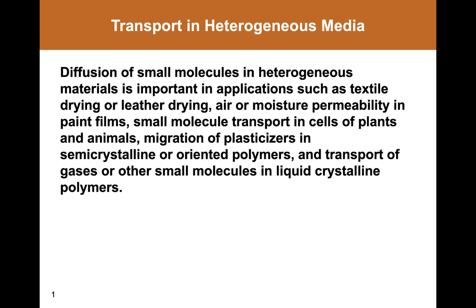And so this can be, for example, crystalline regions in a semicrystalline polymer are impermeable, but the amorphous region surrounding these crystalline regions typically is not impermeable. And so penetrant molecules that are diffusing under a concentration gradient through such an environment will have to go around those crystalline regions, and so the transport equations are modified as a result of the structural heterogeneities in the material.